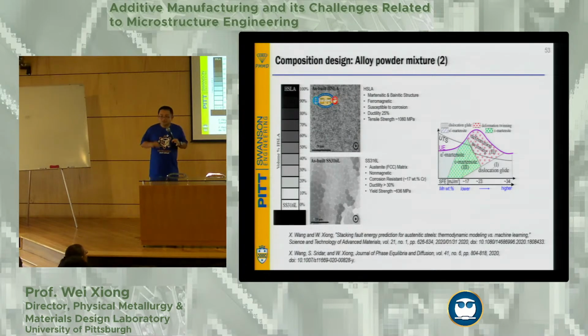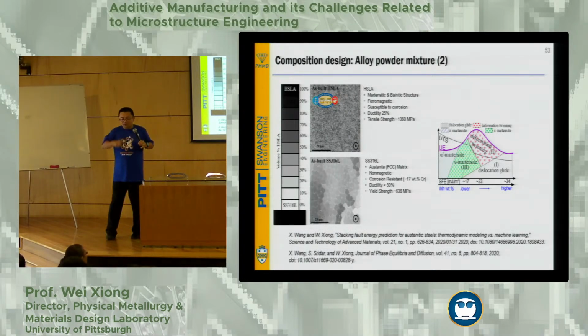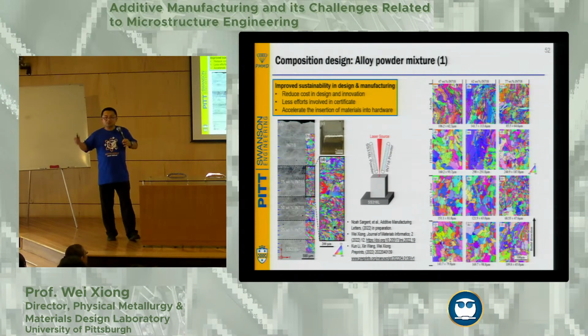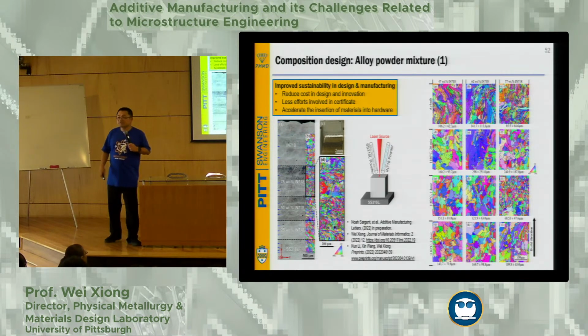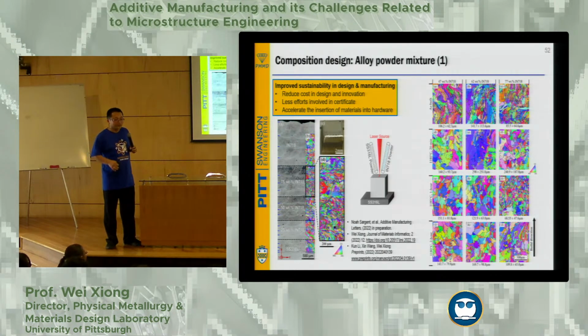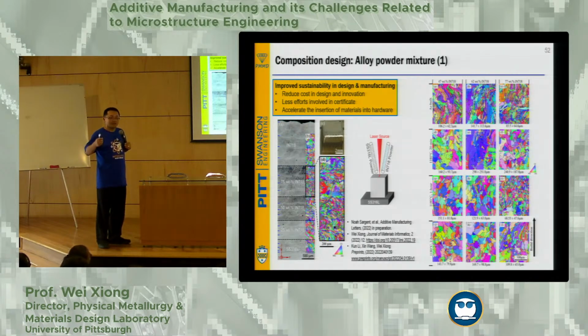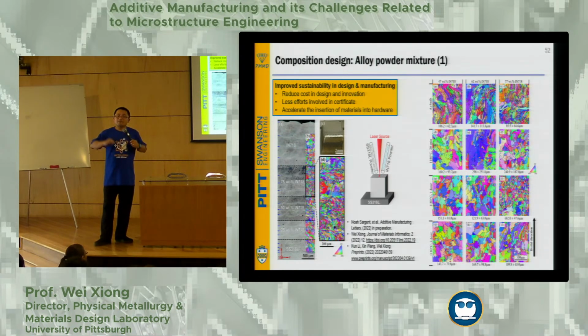But with this concept, we further utilized this material to process with laser powder bed fusion process. This is another one, focusing on 75%, 77%. This is actually interesting - we just finished one of the studies by one of our talented undergraduate students, and it turns out with this technique, focusing on 77%, we still can get much better performance, even compared with some of the original Inconel 718.